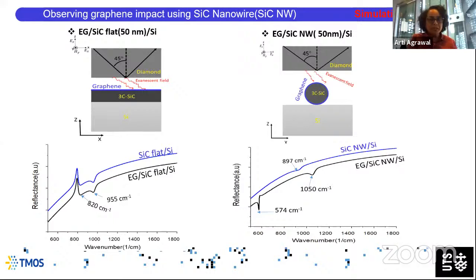Now, moving from a planar structure where our silicon carbide was slightly thick, we have reduced the thickness of the silicon carbide on the left-hand side to 50 nanometers. When the silicon carbide thickness is extremely small, we find that the behavior of the features changes a little bit. Instead of having very prominent dips at about 950 centimeter inverse, the dips become smaller and the peaks at about 800 shift a little bit. But again, the behavior is not substantially different, although the thickness is of course making a difference. So what we recognize is that the thickness of silicon carbide is important.